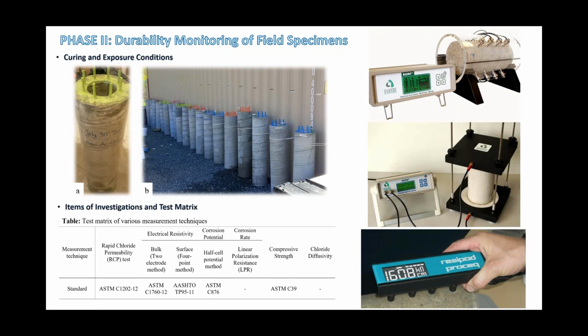One of them is kind of my main focus, which is electrical resistivity, which, as I mentioned earlier, has a direct relationship to the concrete durability. There are some non-destructive methods that you can use. I use 2 different products. One of them is Giatec, which is a Canadian-based company, and the other one is Resipod. Resipod has the capability that you can simply go on the site and measure the resistance of the concrete. On the photo on the right-hand side, you can see 4 probes, and these probes induce the current on the outside and measure the voltage inside. Using Ohm's law, you can get the resistance of the concrete.